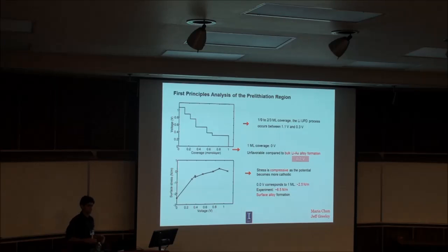The value of the stress is less than the experimental value, and the reason is that this model is just for a monolayer of lithium. But in the experiment, we showed that we had at least 6 monolayers of lithium on the surface.